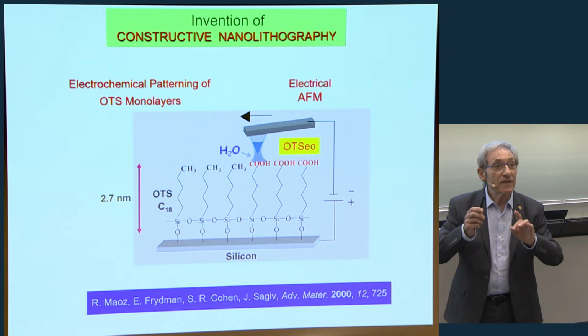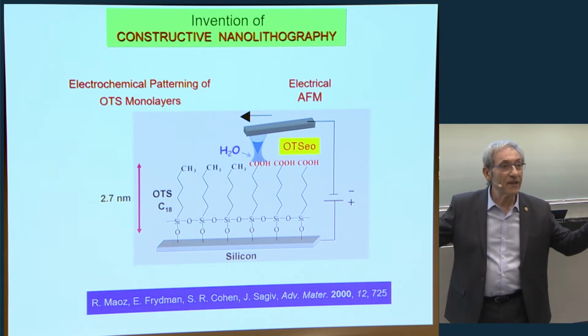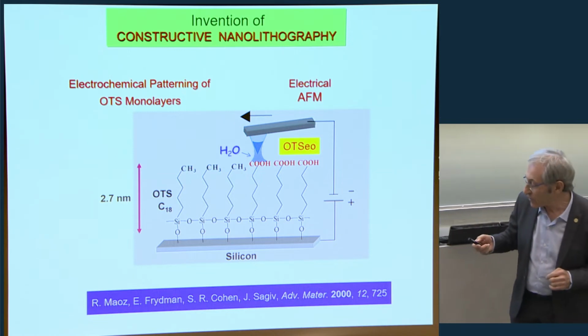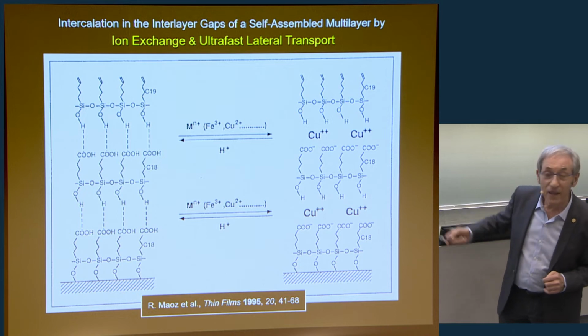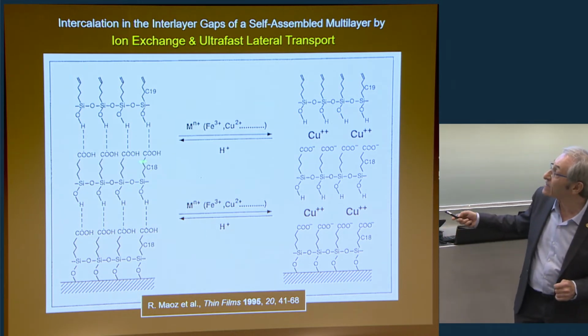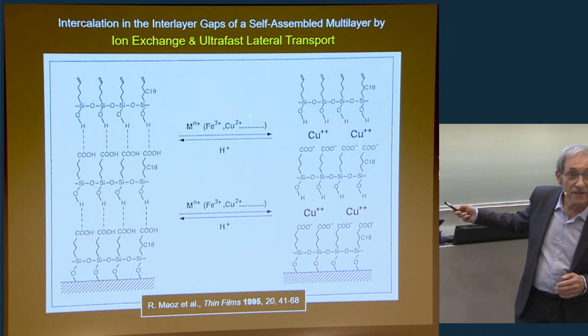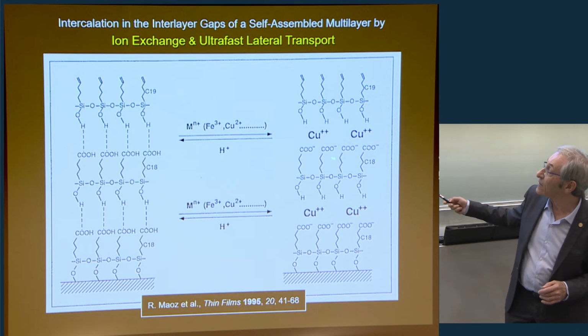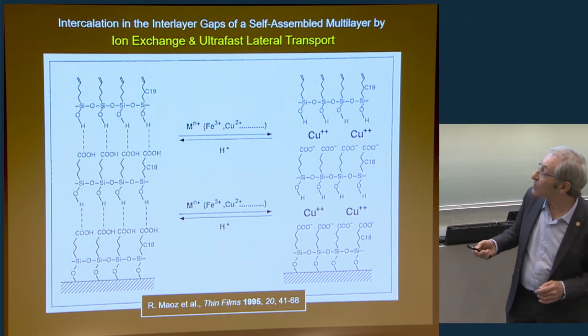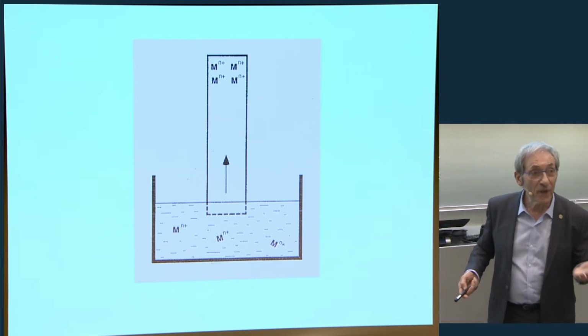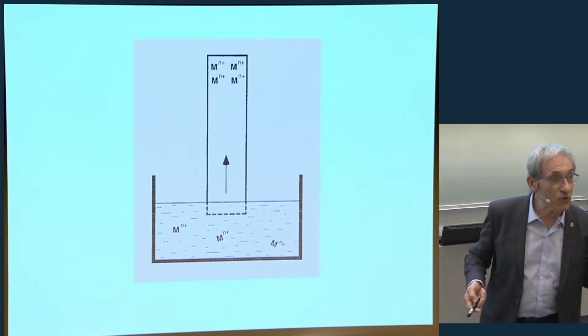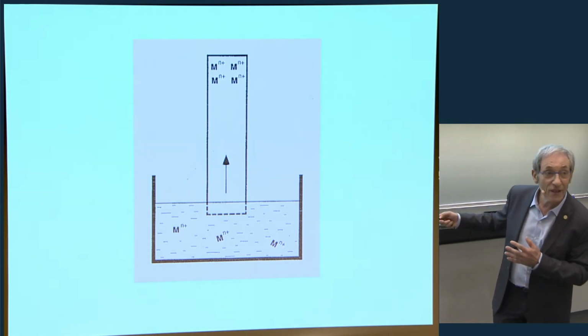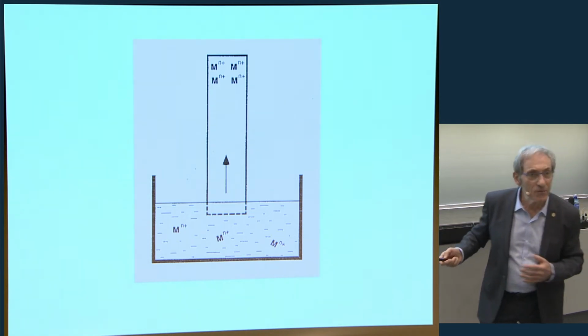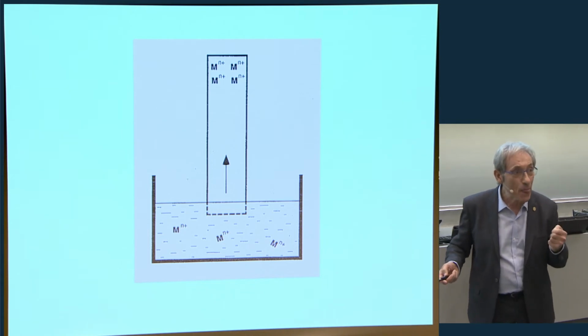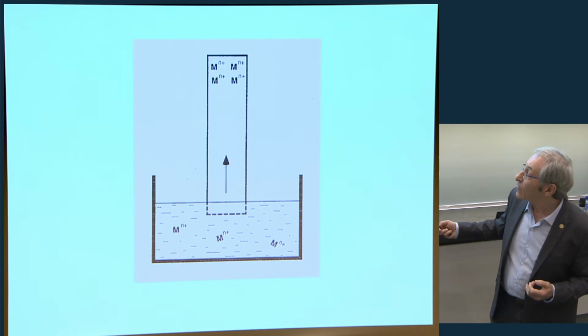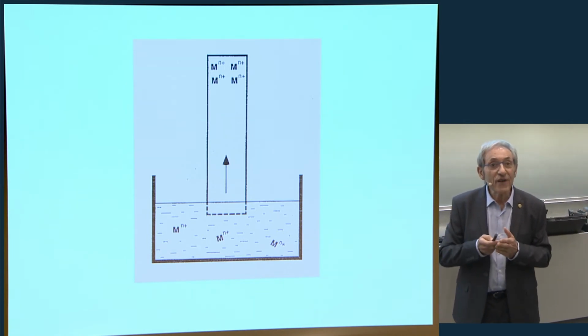They are densely packed. And we also found with infrared spectroscopy that we have lateral hydrogen bonds. Now, from our previous work, we knew that we can intercalate ions here. The intercalation involves replacing protons with ions, different ions, in this case copper ions. It means you start with free carboxylic acid, you end with copper carboxylate. This is a process which is triggered, controlled by a chemical potential gradient. You actually place a slide coated with these multilayers, and then the ions move with extremely high speed, unusual speed, because it's not just diffusion. They are driven and replace protons. So we know that we can have extremely fast ionic motion.